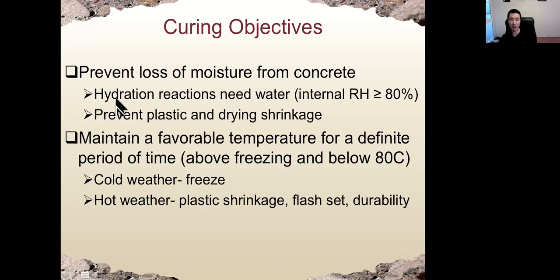That's one reason: prevent loss of moisture from concrete. Another reason is to maintain a favorable temperature for a certain time, normally around 1 week. If the temperature is too low, below freezing, the concrete will first stop hydration, and second may crack because when water becomes ice, the volume expands. We call that freeze and thaw attack. It is dangerous, especially when concrete is young at early age, so at early age the concrete cannot be frozen.